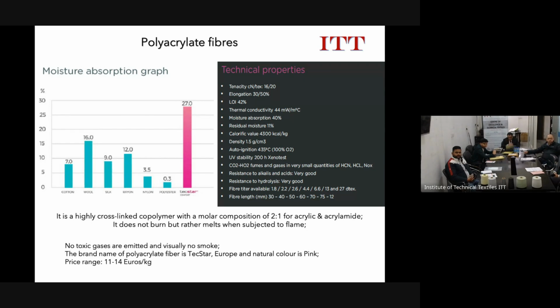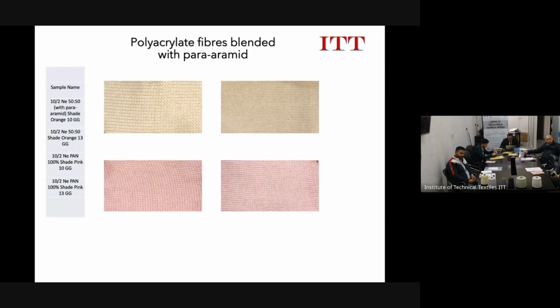Polyacrylate fiber. Again, we bought 50 kg of this fiber a month ago, and we are finding it very interesting when blended with aramid. And you can see that the moisture absorption is 27%. So it's very comfortable. We have developed two blends, and we are doing a lot of testing. We are comparing these fibers with other materials, and you will see some polyacrylate fibers being used in India very soon.